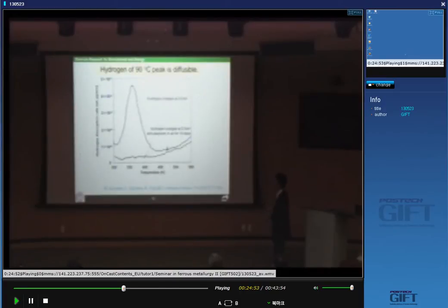Another information, this hydrogen can go away when you keep the sample at room temperature for 10 days. After 10 days keeping, you cannot see any peak on the TDS profile. This profile changes to this. This means hydrogen of 90 degrees C peak is diffusible one.